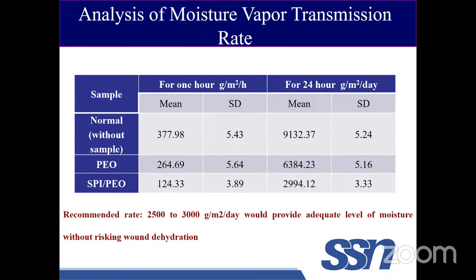The recommended rate for wound healing is about 2500 to 3000 grams per meter square per day, right? That is an adequate level of moisture vapor transmission for a wound dressing material in order to maintain proper hydration in that area, so that dehydration is avoided. If the area is dehydrating more, then healing will happen at a slower rate, and the risk of infection by microorganisms will be higher, right? From the table, you can clearly observe that the sample blending SPI with PEO, SPI/PEO, was in the recommended rate, right? The moisture vapor transmission rate is 2,994 grams per meter square per day.